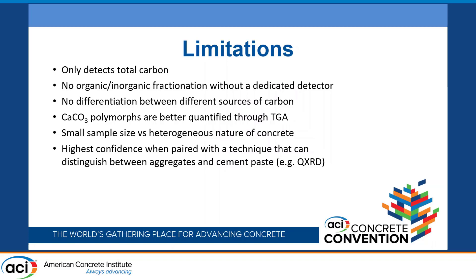As with many techniques, you're talking about small samples — a gram or less — and concrete can be a very heterogeneous material. You have to be careful about your conclusions with respect to the sample you took. Is the sample you analyzed representative? Given that you can do the testing in under a minute, it gives you the latitude to do lots of samples and approach that representativeness problem. Ultimately, this fits as part of an analytical strategy. Some of the work we've been doing to calculate carbonates is improved by analyzing the sample with quantitative XRD to figure out the sand fraction and use that to improve your conclusions from the carbon analysis.